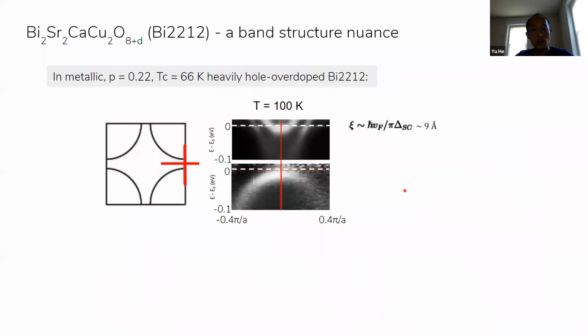But we notice there's a small band structure nuance, where if we were to look at the local band structure along the Brillouin zone boundary, we see that along the boundary, there is a very shallow Van Hove point, a very shallow local band bottom, or a very shallow band top if we were to look at the perpendicular direction, that are very close to the Fermi energy. And they're very flat. They're flat to an extent that extend all the way almost to 30% of the linear dimension of the Brillouin zone.